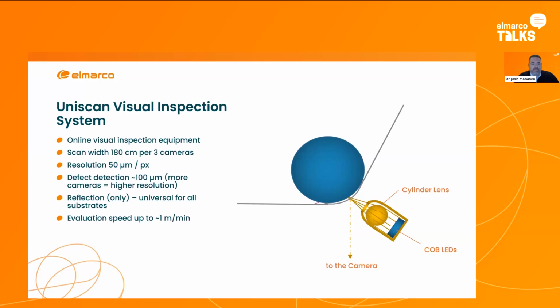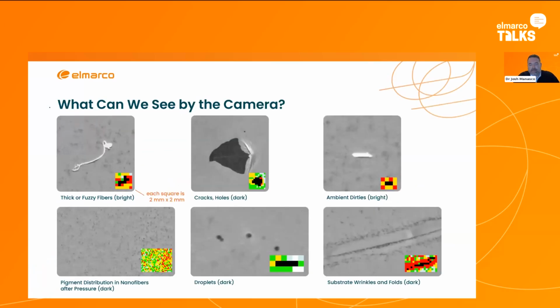So when we're looking, it's a reflection mode. It mounts at the end of our equipment. It's quite easy to use. It took quite a bit of development to be able to build libraries of these defects and everything. But it's quite handy for us to verify that we're seeing what we're seeing in the process. So it can be a quality aid, it can be a process aid for whenever there's something wrong with the process or something with the quality of the material. So these are the types of things that we've found: some fibers, some extra fly of fibers, some holes, dark spots, things where there might be wrinkles in the process. So that's where you can use it to find out if you're forming some wrinkles somewhere in the substrate that's causing you to have these sort of non-uniformities.